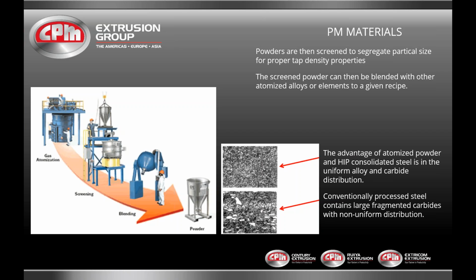The HIP materials, continuing, the powders are then screened to segregate particle size for proper tap density properties. The screened powder can be blended with other atomized alloys or elements to a given recipe, but generally most of our materials, or maybe all of them, are pre-alloyed, so they're alloyed before they get atomized.